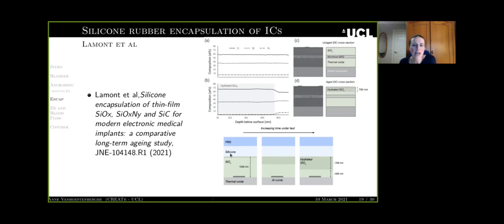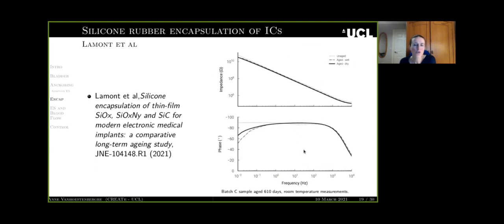So what we think happened is that the silicone rubber, we know, is not a barrier to water, so water vapor penetrated through it. No liquid water formed over the passivation, but the silicon oxide itself very slowly absorbed a little bit of the water vapor that had penetrated through the silicone rubber, forming a hydrated layer. And this was sufficient to cause changes in impedance and in phase that were progressively observed. This is one of the batch C samples showing you the effect of drying it. As it was dried after aging, the phase recovered slightly.